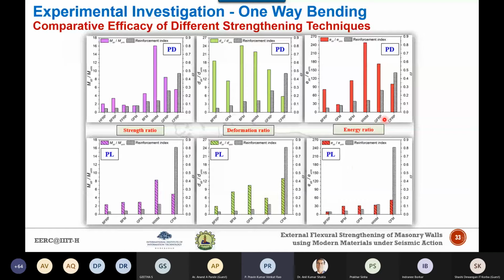So, as I said, these strengthening methods not only increased the flexural strength, but also enhance the deformability of the wallets before the failure, which allows them to dissipate more energy, especially in case of cyclic loading, especially in case of earthquake loading. So as a result, the designer has difficulty in choosing the most appropriate technique, and therefore the selection of the technique depends upon several factors. So for this, an effort has been taken to identify the relative efficacy of different techniques to help the designer to choose the most appropriate strengthening system. And for that, the strength ratio, deformation ratio, and energy ratio have been developed.